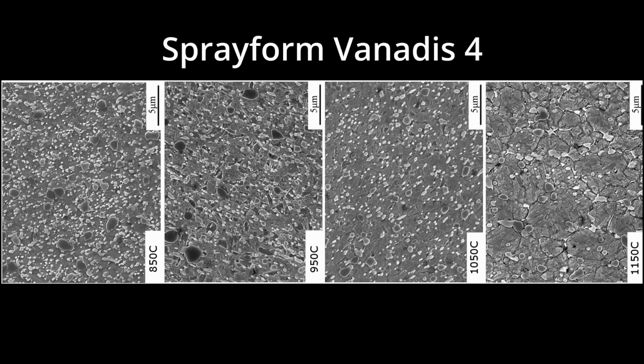And holding it for a long time at high temperature is as likely to coarsen the carbides as it is to shrink them. So here was a study on a spray form, Vanadis 4. Spray form is a technology that's just a bit worse than powder metallurgy. And their optimal forging rolling temperature was 1050 Celsius. If they went hotter, up to 1150 Celsius, the carbides coarsened too rapidly.